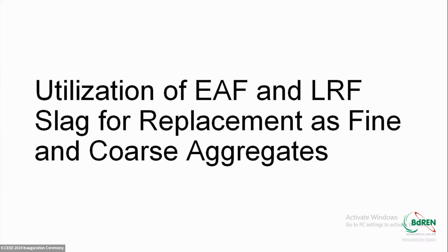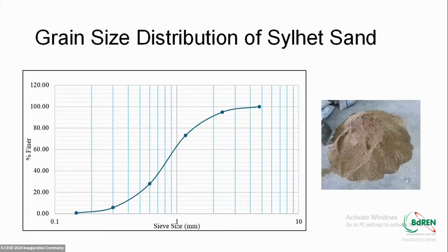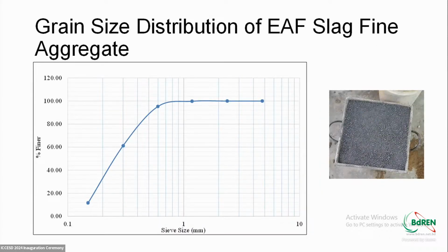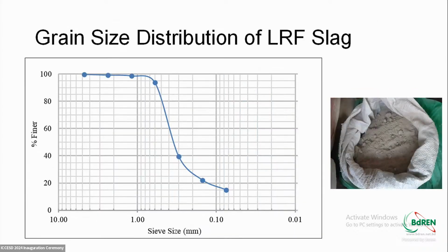Now, we also studied if EAF and LRF slag can be used as replacement of fine aggregate or coarse aggregate. For that, if we see the grain size distribution, this is the grain size distribution of Sylhet sand. The samples we used for fine aggregate replacement of EAF slag were much finer compared to Sylhet sand, which is not good. LRF slag was already, we had to crush EAF slag, and we can actually make coarse aggregate with EAF slag, but with LRF slag, coarse aggregate is not possible - it is always in powder form. So LRF slag can be used as replacement of fine aggregate or as clinker, but not as coarse aggregate, again because the particle size is much finer compared to Sylhet sand, which is not good.